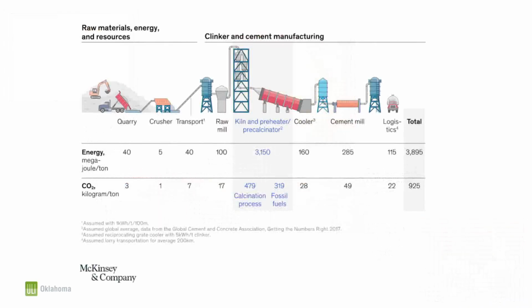Now, if you look at the whole process and start mapping the carbon footprint of it, most of that carbon is actually coming from that kiln and the preheater before you go into the kiln. On the CO2 kilograms per ton, we have about 479 just on the calcination process, which is the reduction of that limestone, CaCO3, into just the CaO with CO2 remaining. So just the calcination process of reducing that limestone into a more usable calcium oxide is a very, very CO2 producing effort. The other part, 319 kilograms per ton, is the fuel that we use in order to heat up all that material to turn it into clinker.